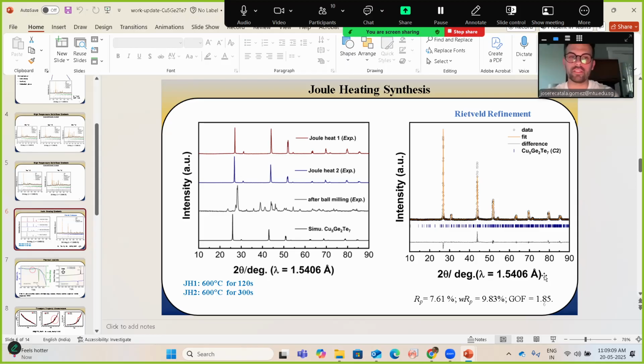I don't know. You tell me. I mean, you could see that it is moved, based on the peaks associated with the Rietveld refinement, right? It's moved towards higher 2 theta. No, if you see, one side is down, below around 27, one side is up. It indicates it's not simply moved. It's like different edge scales. Which edge scales? I mean, the main peaks. I don't know this one.